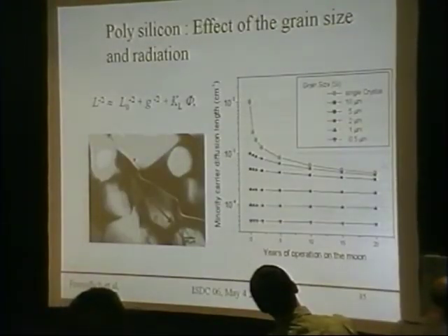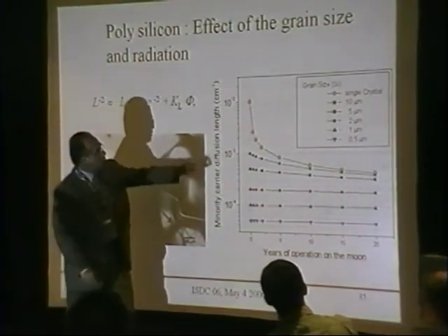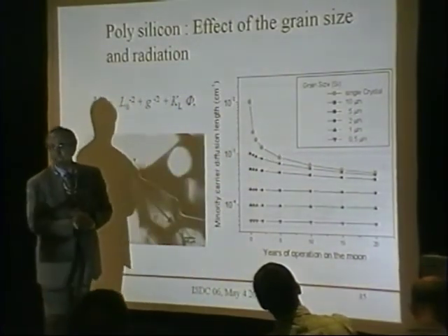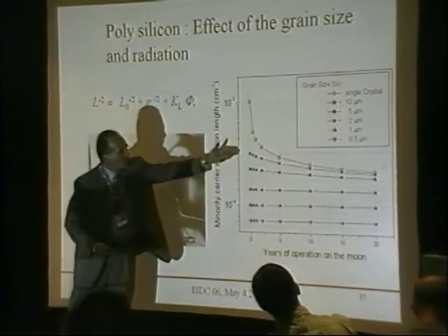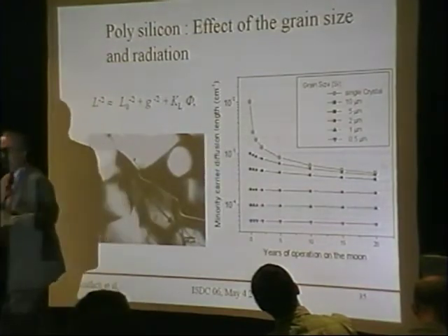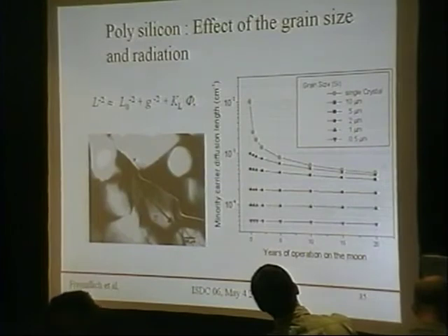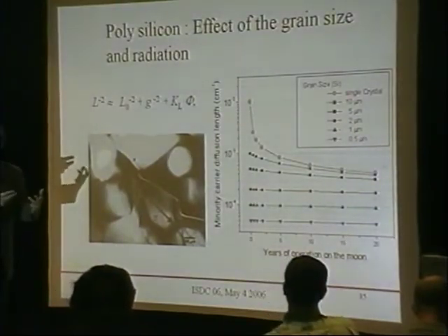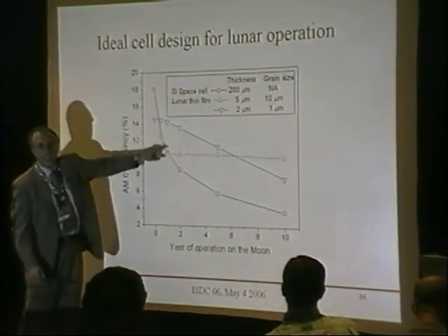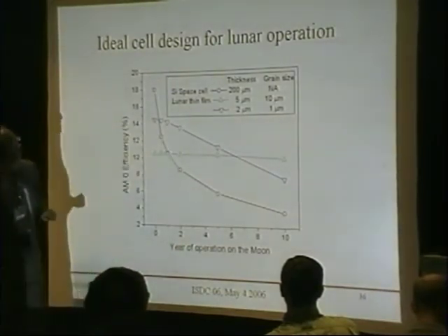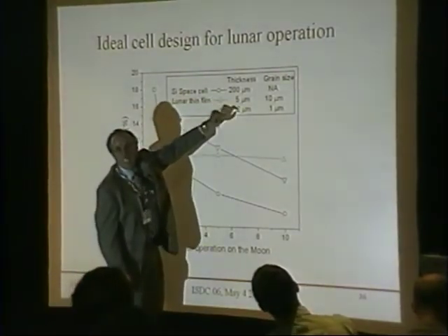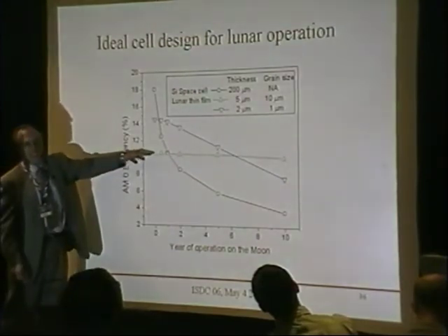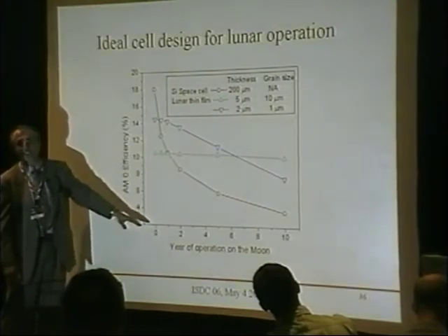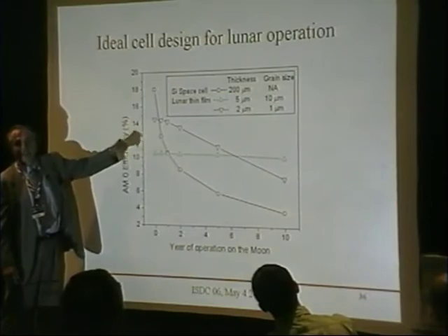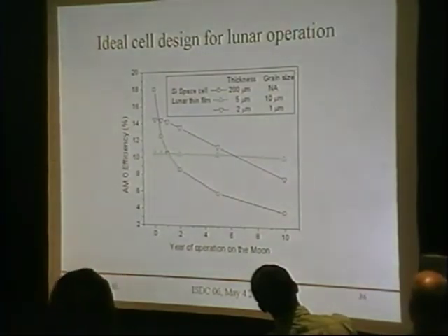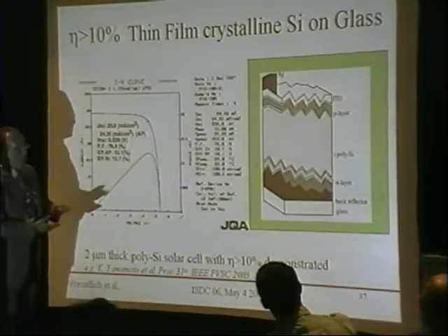Next. Now, if I add radiation into the system, I find that the diffusion length in silicon degrades very fast if it's high-quality single crystal, but as we go to poorer quality material, the degradation is driven by the grain size itself. So the holy grail is to design a cell that is matched to the grain size. Next. It's the same graph that we had for silicon earlier, with no cover glass here. You can essentially get a completely flat response solar cell that could operate for 10 years on the moon. Because it's very thin, the degradation from radiation will be negligible, and it's designed to be thin. Next. I'm sorry, if you can come back one second.